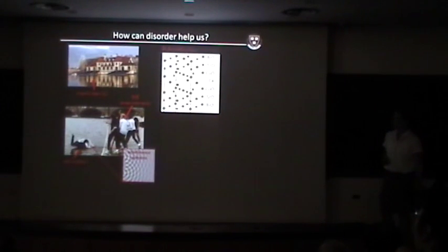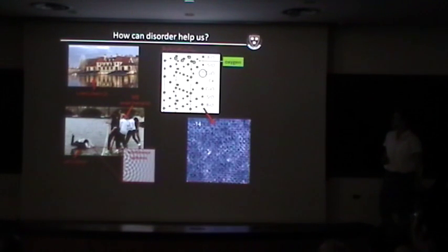So I'm going to take that concept and apply it to these materials that I want to learn about, and take a clean material, and then introduce some kind of disorder, such as substitution impurities, or the oxygen dopants themselves. And then when the electron waves, as opposed to the water waves, scatter off of this disorder, they're going to create interference patterns in the same way as the water created an interference pattern in response to this perturbation.